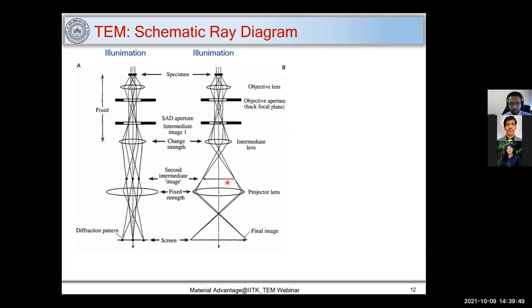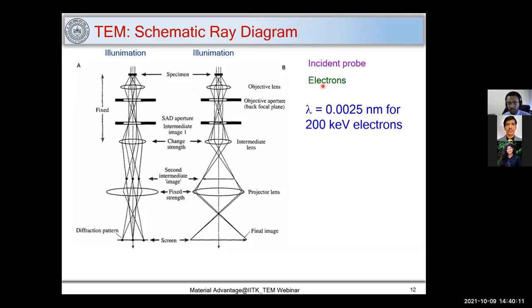I can form an image by just diverging it more, the beam goes in this way, and thus it can create a final image. So we can get both a diffraction pattern as well as an image in TEM just by changing the current flowing through the intermediate lens. So we have an incident probe, we have electrons, and when I use 200 keV electrons, the wavelength lambda is much smaller, like 0.0025 nanometers.